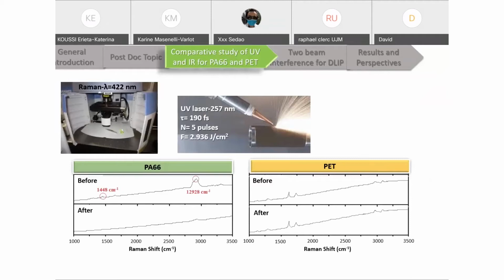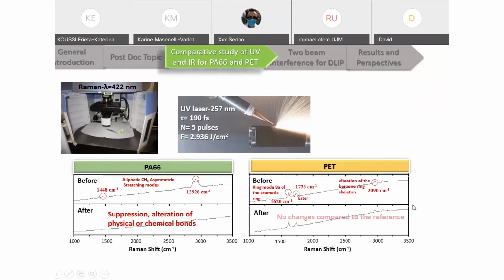So before, for PA66, before irradiation, we can distinguish two characteristic peaks that are attributed mostly to CH2 asymmetric stretching modes. After the irradiation, we can see suppression that maybe means the alteration of physical or chemical bonds. For the PET sample, before the irradiation, we can distinguish some 3 characteristic peaks attributed to ring mode 8A of the aromatic ring, to ester, or to vibration of the benzene ring skeleton. And after the irradiation, all these peaks remained unaltered and no changes were observed compared to the reference.